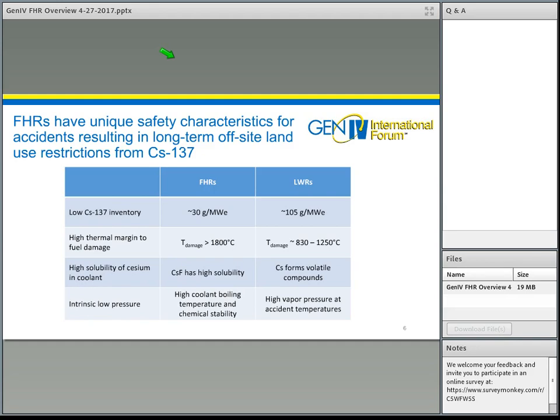The fourth and other key attribute is intrinsic low pressure. The molten salts have very high boiling temperatures, up above 1400 degrees centigrade, and therefore they do not boil during transients and accidents. And they're also chemically stable compounds. The principal reason that we do use cover gas and cover gas control with the fluoride salts is to control for corrosion. But the fluoride salts have low chemical reactivity. And this is in contrast again with, say, light water reactors where the coolant has high pressure.